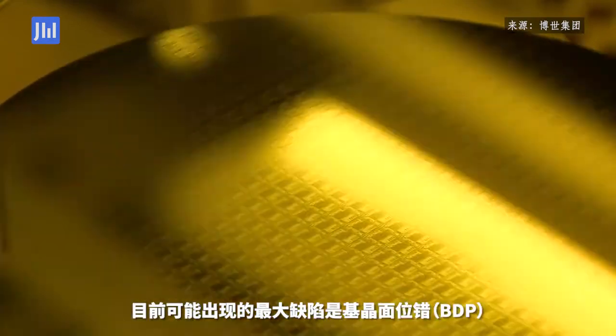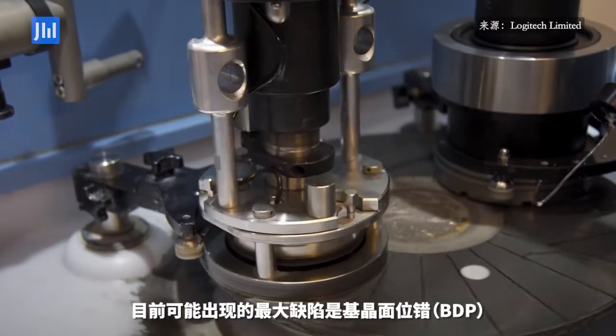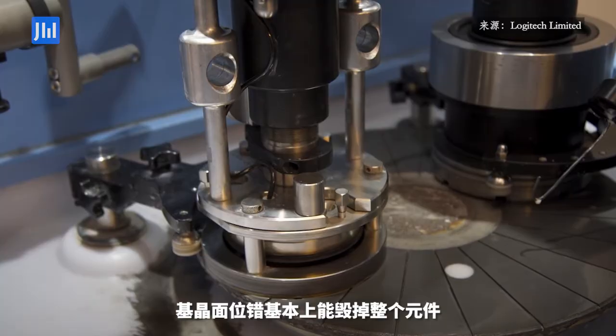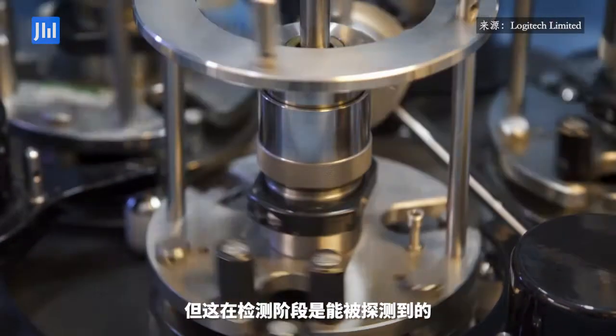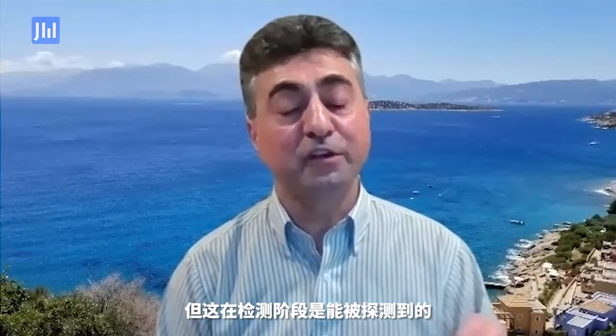At this point, we'll control most of the defects. The really big catastrophic defect at this point is basal plane dislocations. Basal plane dislocations can basically kill the device, so to speak, but those can be detected at the test and inspection level. The one situation that is still kind of a reliability concern is the threshold voltage instability.